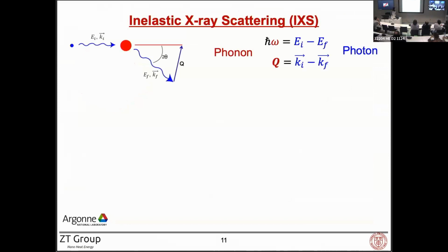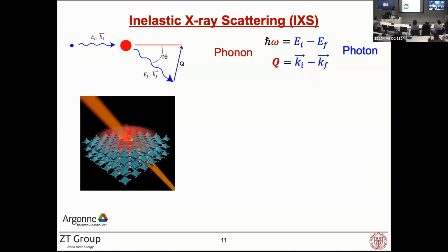So very briefly, inelastic X-ray scattering is a photon-in, photon-out spectroscopy. By monitoring the energy and momentum change of the photon, we can extract the frequency and wave vector of the phonon. We do this for different wave vectors, and then we can map out the phonon dispersion. We carried out the measurements at Argonne National Lab in the transmission geometry.